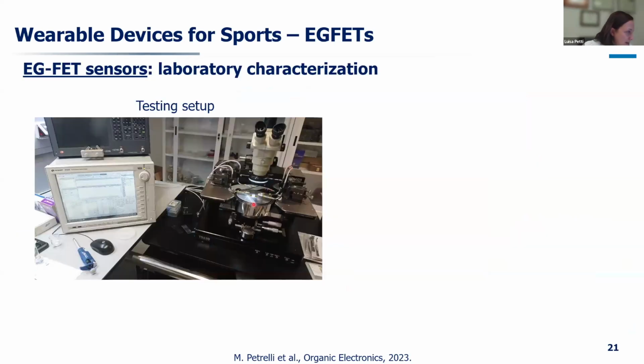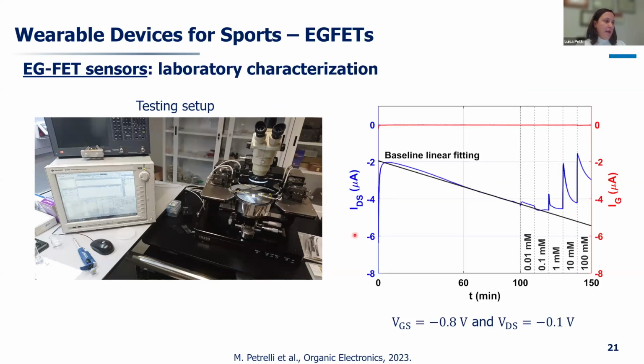This is shown a little bit here. So we have the sort of PDMS chamber where the sweat is added, actually the artificial sweat, because we're doing most of the tests with artificial sweat, mimicking the sweat characteristics. And then the different solutions of ammonium concentration are added in order to calibrate the sensors. Everything, as you see, is tested with a probe station and a parameter analyzer. And you see here also the pipette.